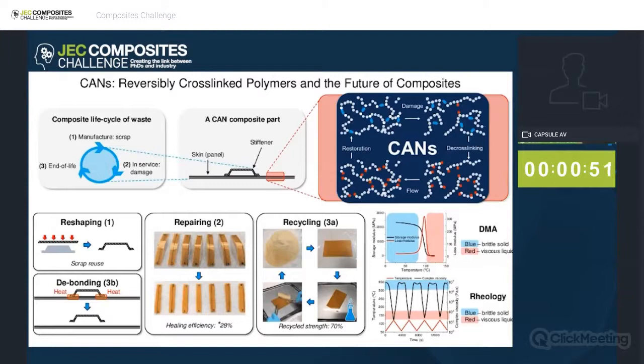And maybe most crucially of all, at end of life, we can develop new recycling methods that work with CANs, such as this solvent-assisted one that I've shown in these photos here. So we put our composite into a solvent, it swells up, and then we can easily separate the fibers and polymer, dry them out, and reprocess them into new composite that has good strength and therefore good value and can be used going forward. So 70% strength there.